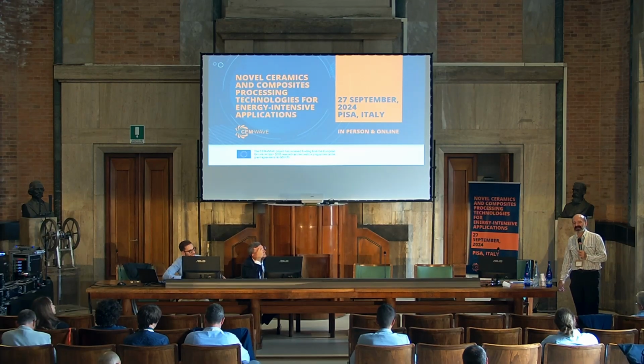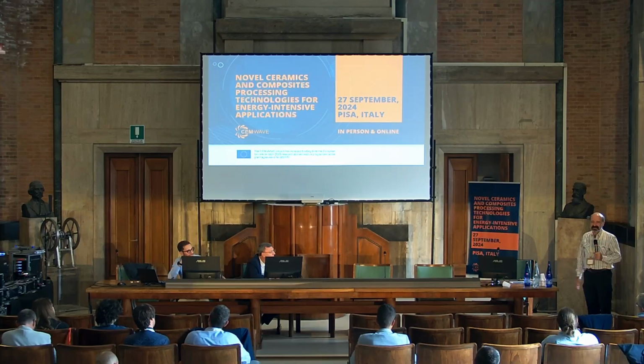In my lab, when I was still a student, there were colleagues of mine doing their PhDs together with me before 92, 93, and they had established that, well, with the same system, you could switch from silicon excess to carbon excess, passing through stoichiometric silicon carbide, just by playing with temperature and the hydrogen to MTS ratio, and also with the global pressure. So, yeah, in practice, all this data should be gathered, collected, and inserted in the model in order to try and extend its realm of action, okay? Does that answer your question?